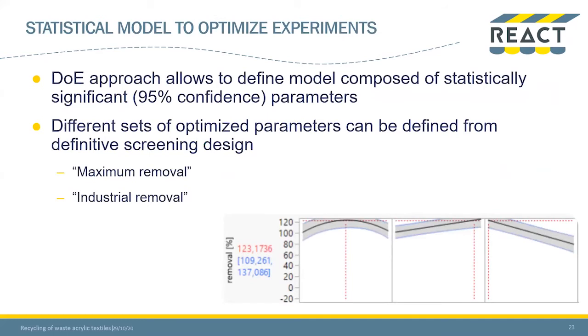And then this design of experiment approach allowed us to define a model of the statistically significant parameters. Since only 3 parameters were of main importance, a response surface model could be defined. And this response surface model allowed us to define different sets of optimized parameters, both for a maximum removal and an industrial removal process.